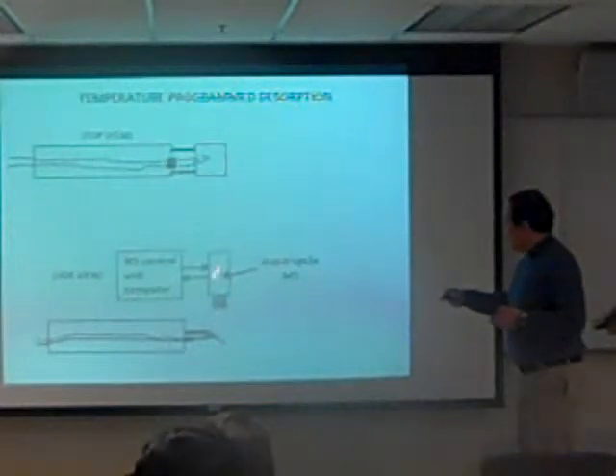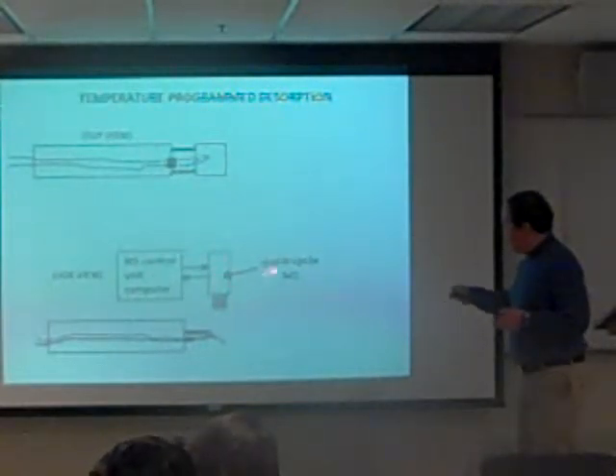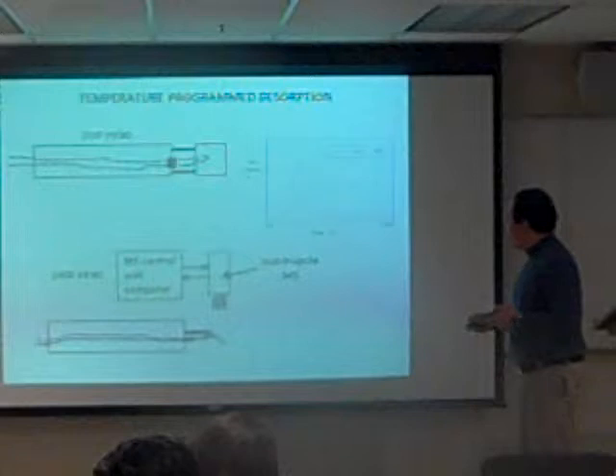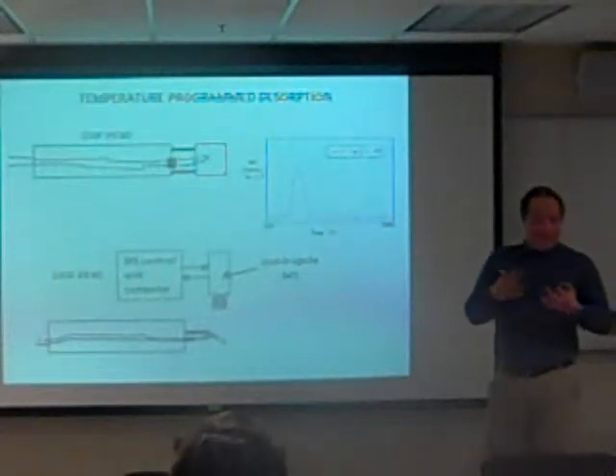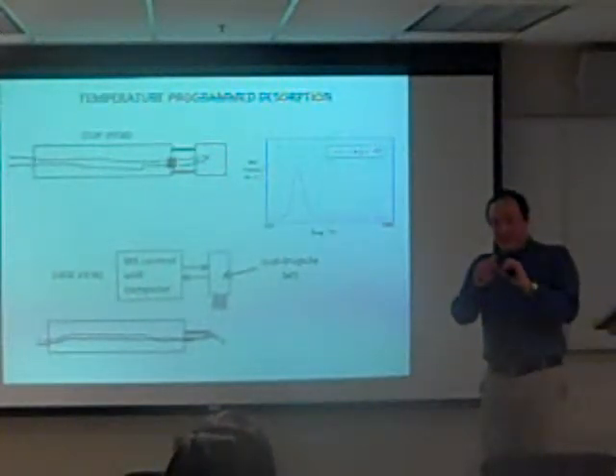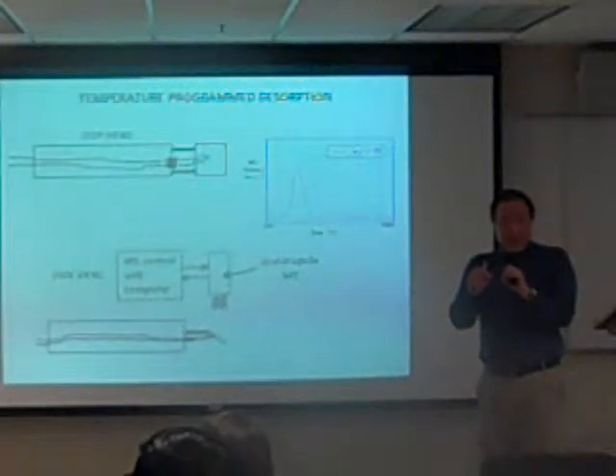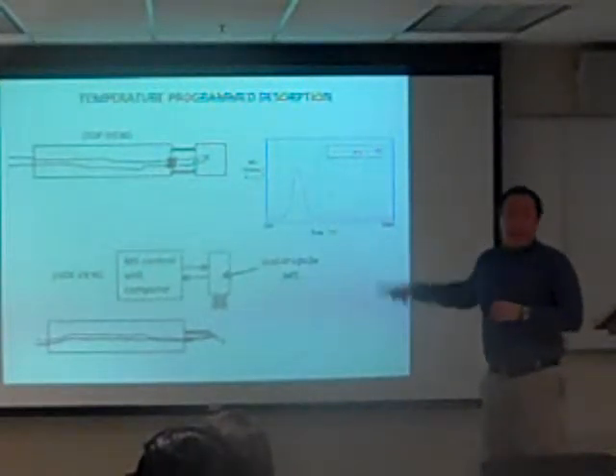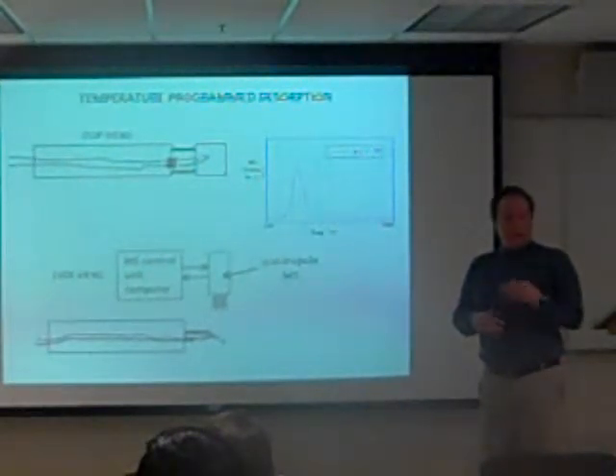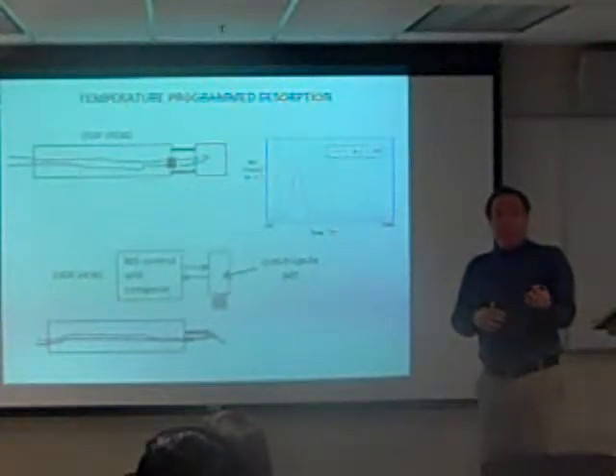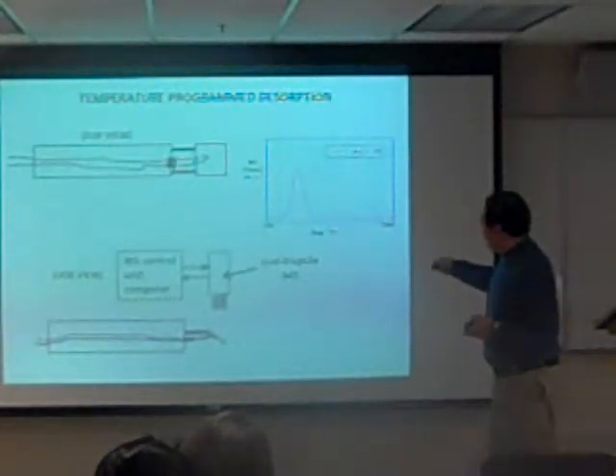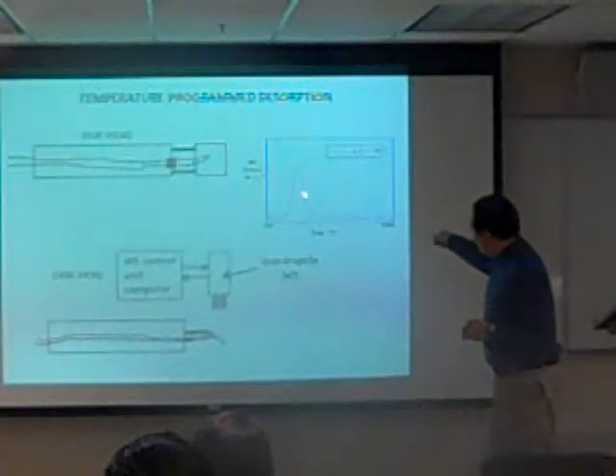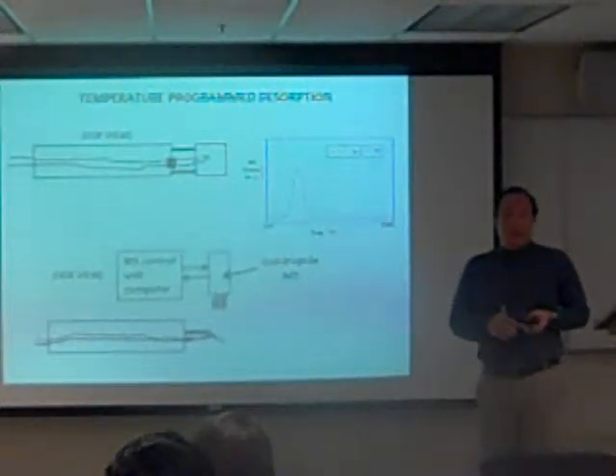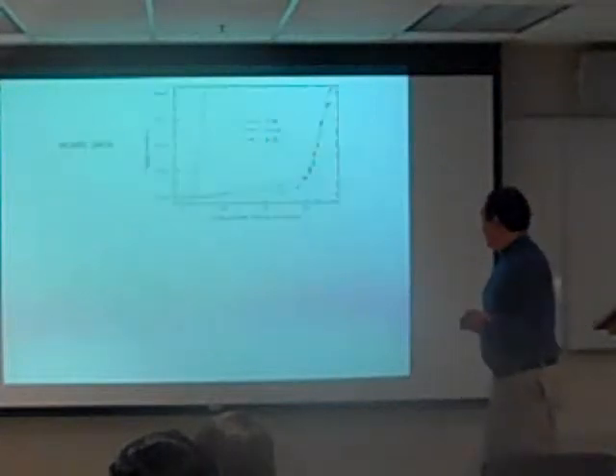Basically, we have a mass spec here, a quadrupole mass spec. It's a type of mass spec where you tune the mass to charge ratio to a certain value, in this case 79, for the phosphate. Then you record the signal, take the integrated peak area, and do a quantitation of the amount of phosphate that adsorbs on the surface.